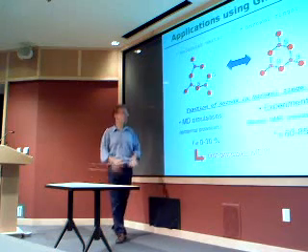In these molecular dynamics simulations, if you remember, the timescales are just, well, the best case nowadays is that you could go maybe to microseconds in classical simulations, and nanoseconds in ab initio molecular dynamics. You cannot get the whole process of how this glass is formed, because for those of you who know the timescales for making glasses, the relaxation times are really long. They can be seconds and so on. So if you do a quick simulation of a couple of picoseconds using molecular dynamics, you don't necessarily get to the correct state of the matter.